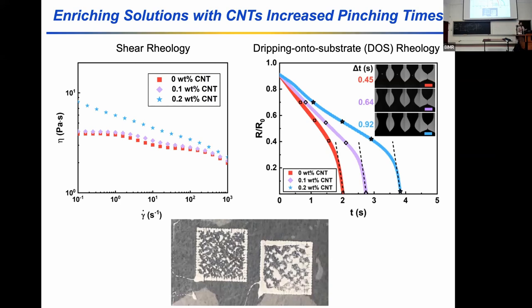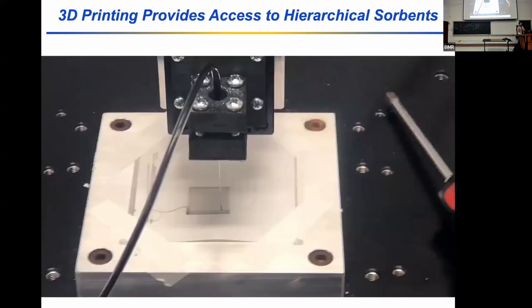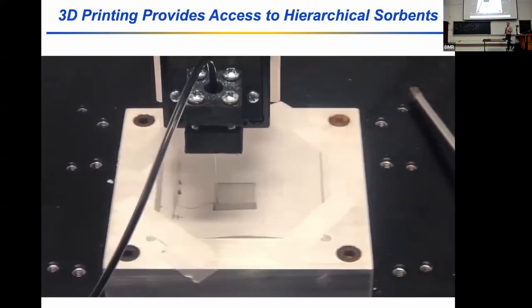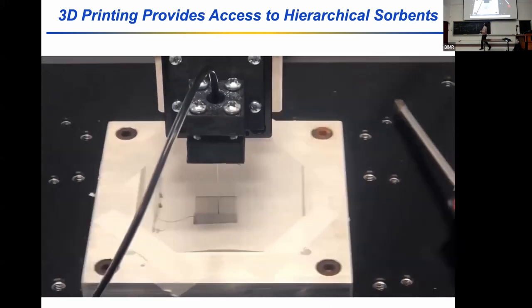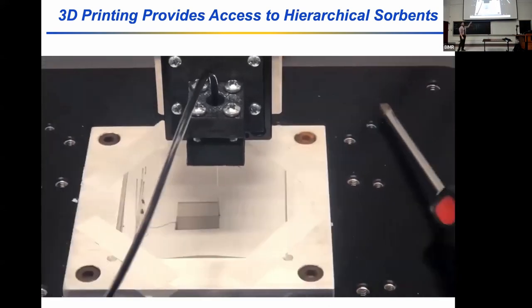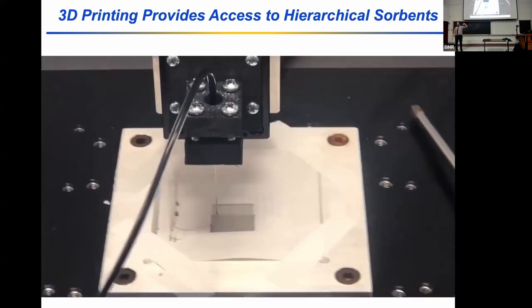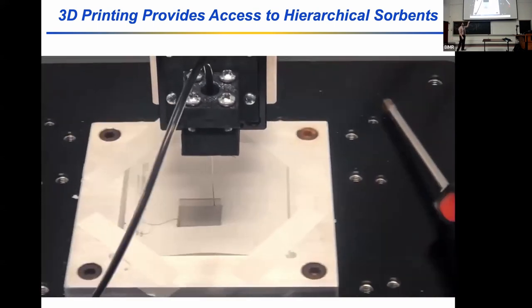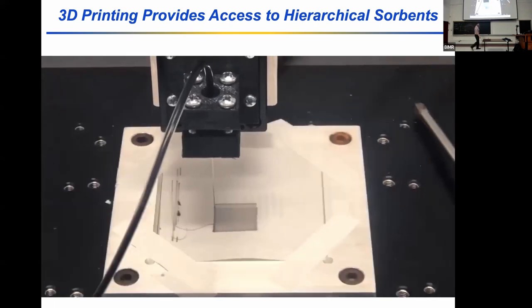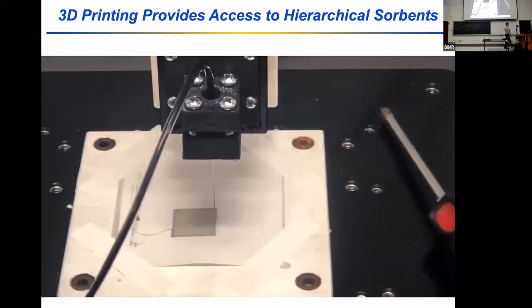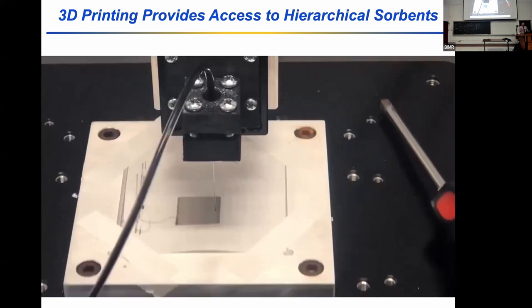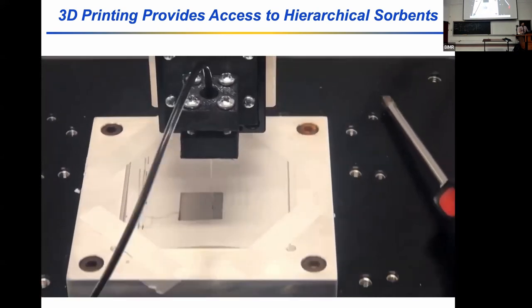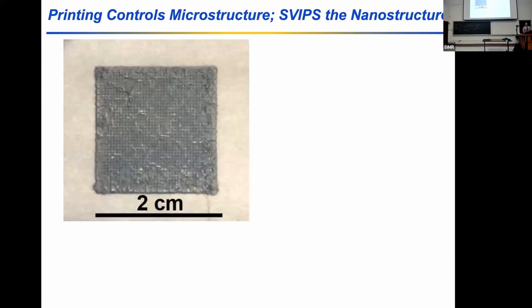If Xiaoling adds in just 0.1 weight percent carbon nanotubes, then this is what the process looks like. We're able to go ahead and with our printer raster back and forth, X, Y, and Z, and create these woodpile structures. And so we go back and forth and you're seeing the solution being extruded in real time. And then she switches to the orthogonal dimension. And after doing that for a set number of layers, macroscopically, you see this structure here in the top left. So now we don't make a mess.